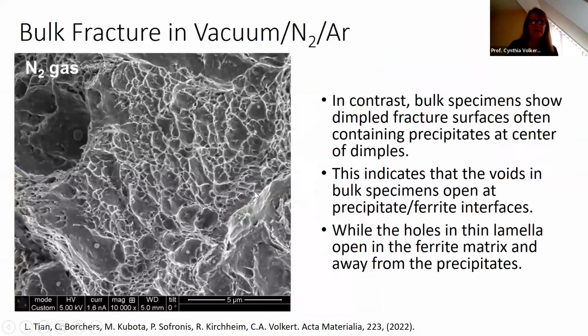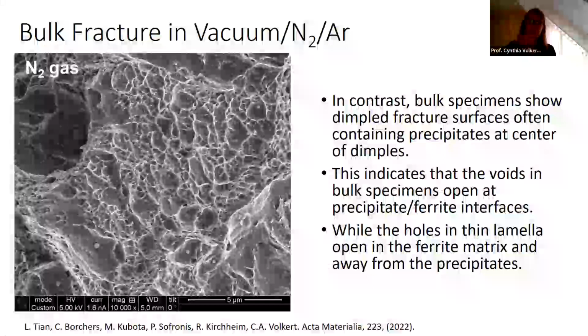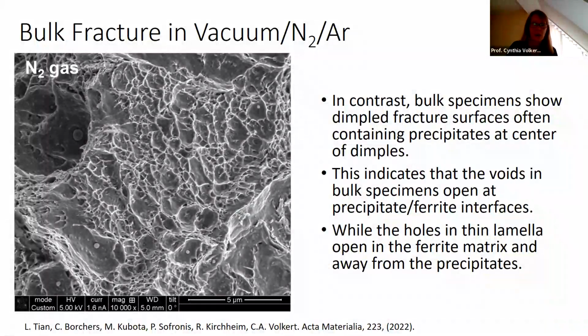Okay, now you saw this picture before. This is the fracture surface of a specimen that's been tested in nitrogen, and you can see there are lots of carbide precipitates at the surface, which we did not see in our TEM case. So what is the difference? In our TEM case, the fracture surface did not contain precipitates. Here there are precipitates. How do we explain this difference?